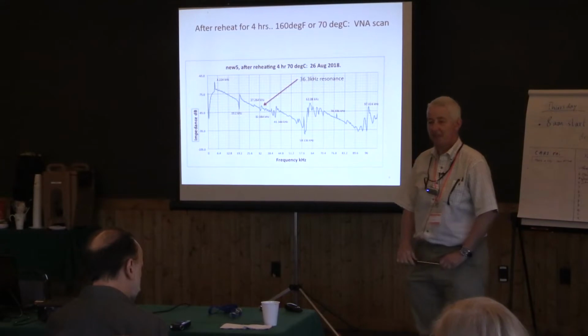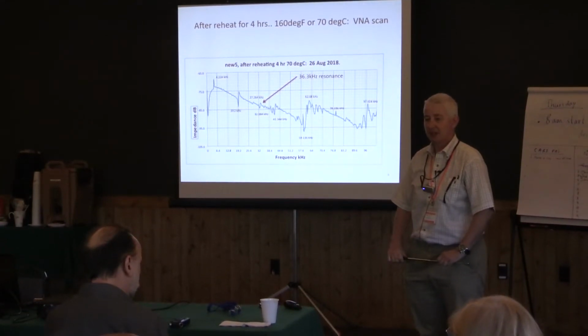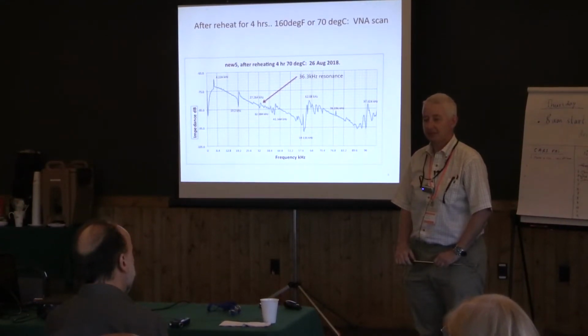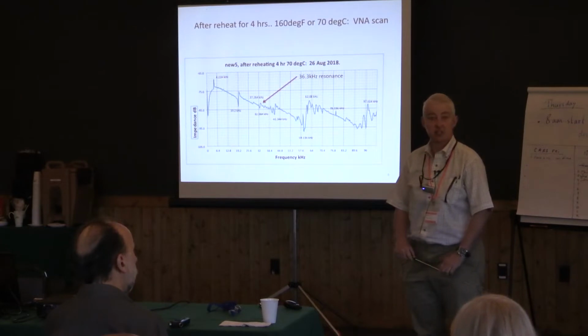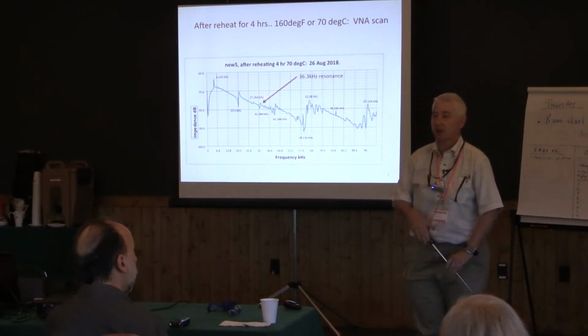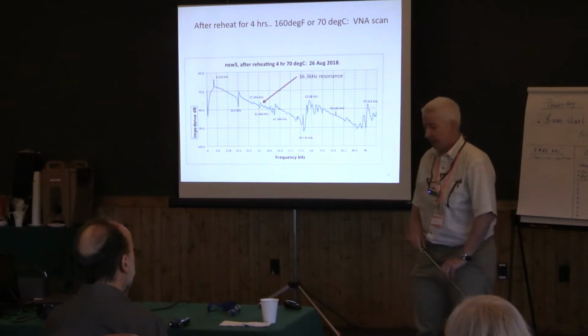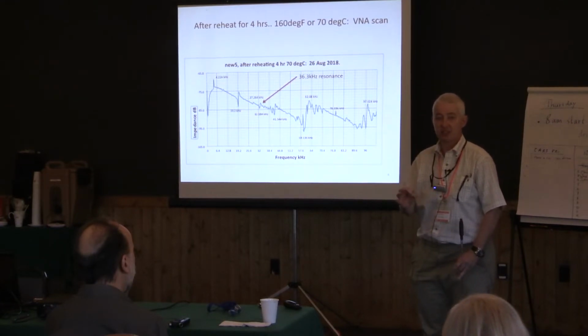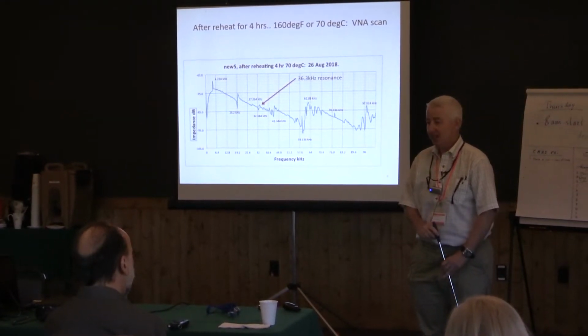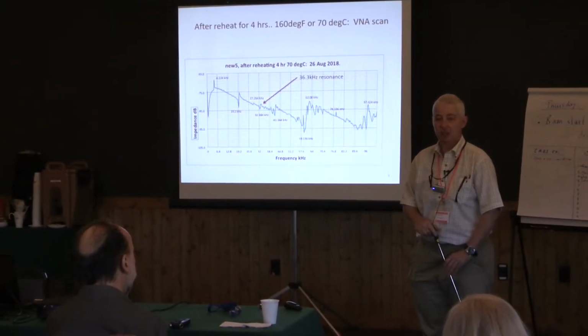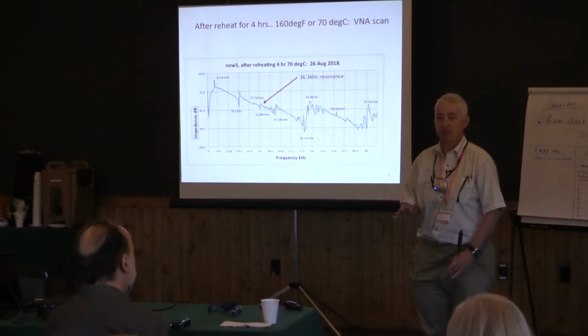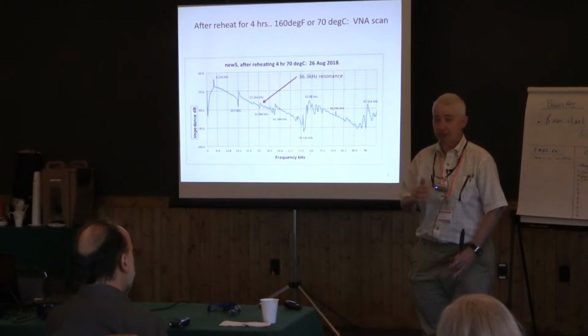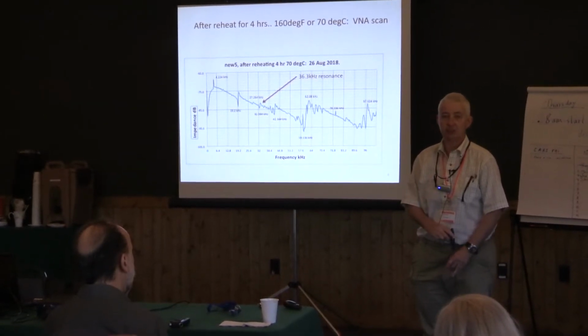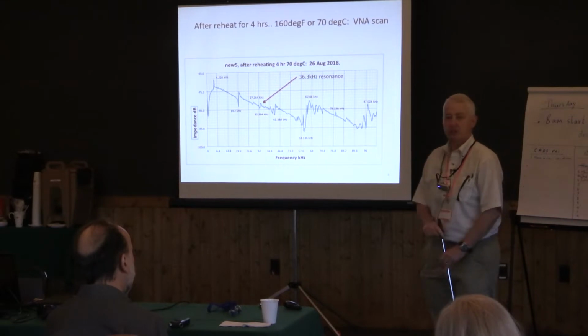But as I understand, TU Dresden actually cured their samples at 67 degrees centigrade, so it's even lower than that? It's even lower. Yeah, probably at Jim's advice, we looked up that specific resin that we bought, and apparently the actual curing is 24 hours at room temperature, and then you're supposed to go 2 hours at 212 Fahrenheit, or about 100 degrees C.